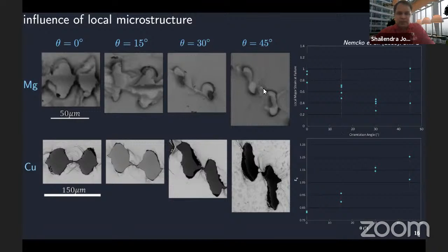And the reason for that is because if you see the finer details of these holes, they can very quickly merge into one another by cracking across, and these crackings are presumably because of twins that are developed in those regions that lead to premature merging of these holes.